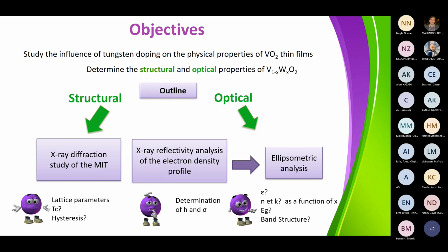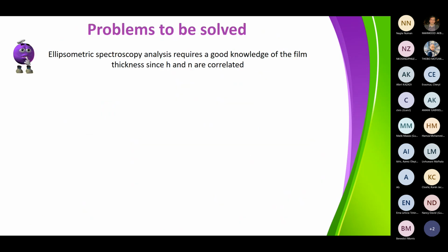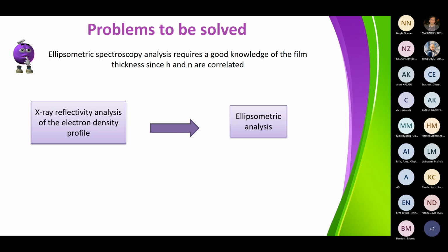And the ellipsometric analysis, well, when you do that, you will get information about the refractive index, typically the real part of the refractive index N, and its imaginary part, which is K, which is related to the absorption of light. If you want to understand the absorption, you need really to understand what is the K value of the index of refraction. And you will see that once you have done that, you can begin to do some very smart analysis of the dielectric functions that you can get from the index of refraction. And then you will be able to find some information about the band structure of the vanadium dioxide. So let's see how we are going to solve the problem.